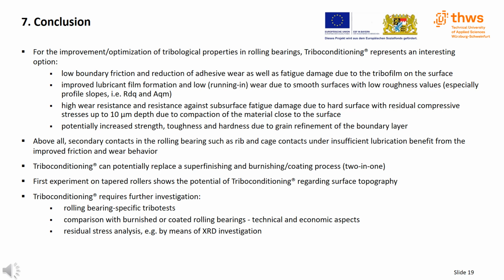Especially secondary contacts in the rolling bearing, such as rib and cage contacts, benefit from the improved friction and wear behavior under insufficient lubrication. Triboconditioning has the potential to replace a superfinishing and burnishing or coating process. An initial investigation on tapered rollers shows the potential of the process regarding surface topography. Further investigations are required to better assess triboconditioning.